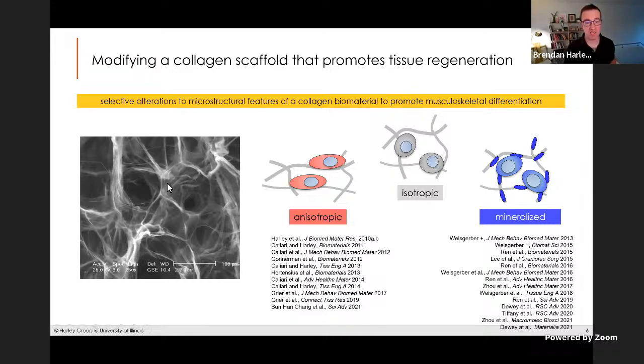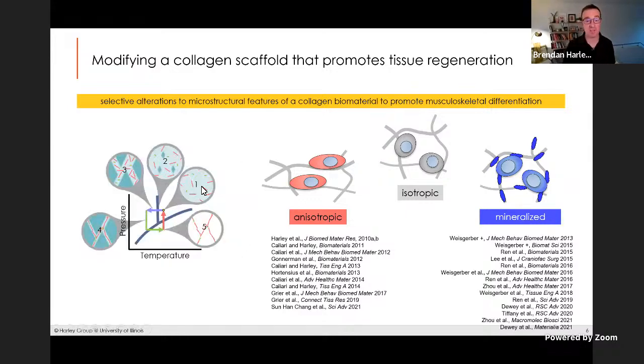So what we're seeing here is a porous network where the lighter regions are the collagen fibers and the darker regions are pores. This material is more than 95% pores, which means it's very easy for cells to move into these large materials. It's easy for nutrients and oxygen to diffuse through these materials. The way we make these is really interesting. We start with a liquid suspension of collagen, which is one of the native proteins in the tissues and organs of our body. We take collagen and other proteoglycans and we mix them in an aqueous suspension to form a solution that looks kind of like milk.